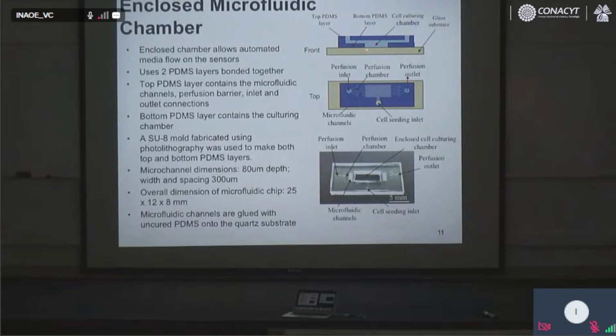Here is the chamber of the cells, and here you put one tube to introduce the cells and the cell media. Here is another tube to extract the media, which was already used by the cells. We use PDMS. Absolutely the classic PDMS microfluidic fabrication. Again, for this fabrication, you also use a mask, and you can print the mask with the printer, because the microchannel dimension was 80 micrometer by 80 micrometer.